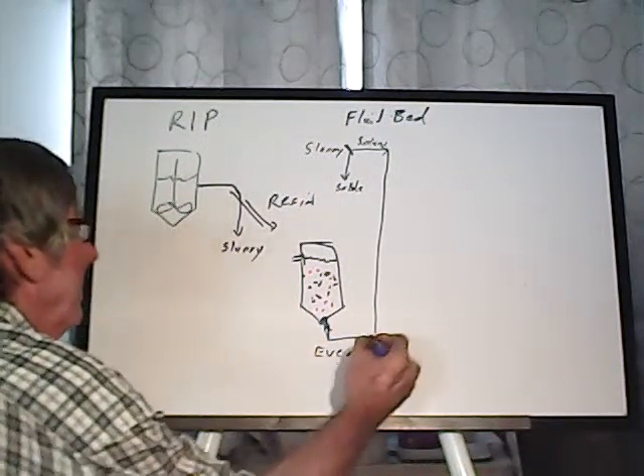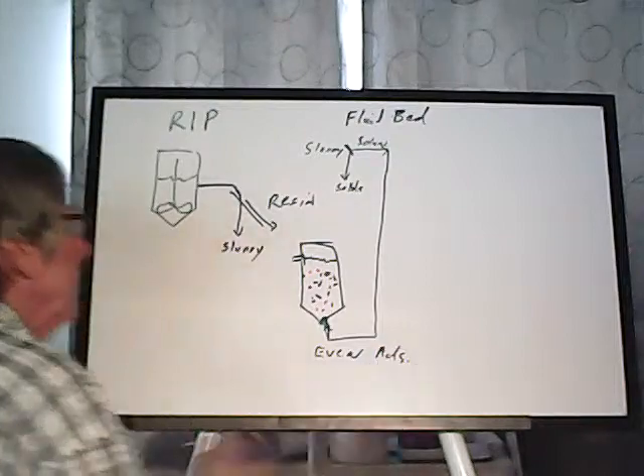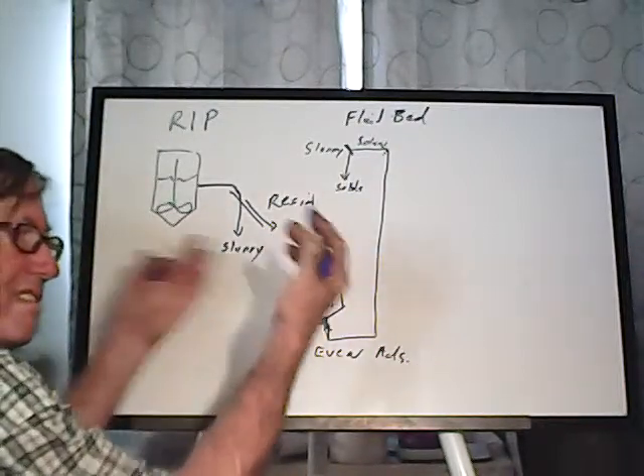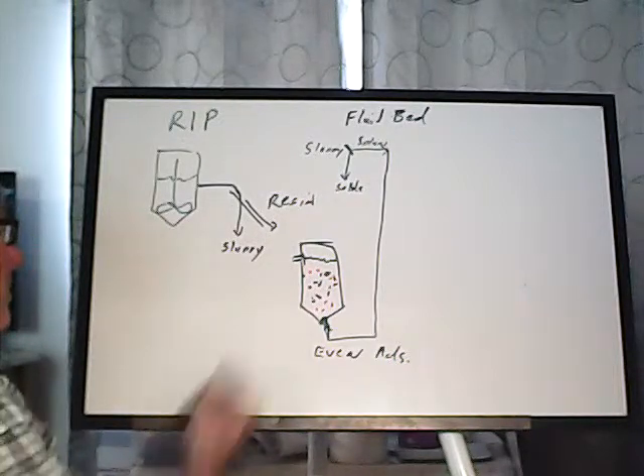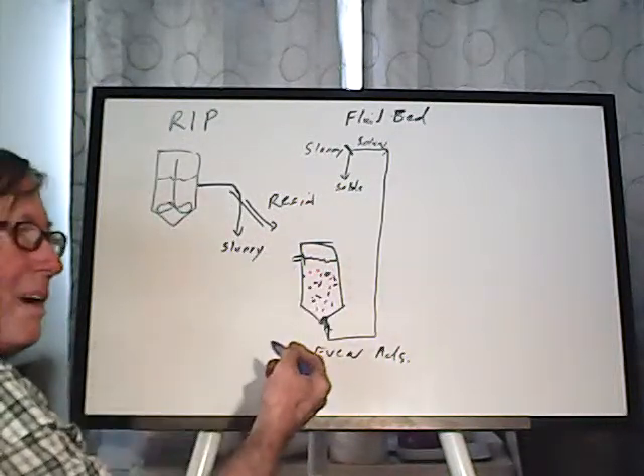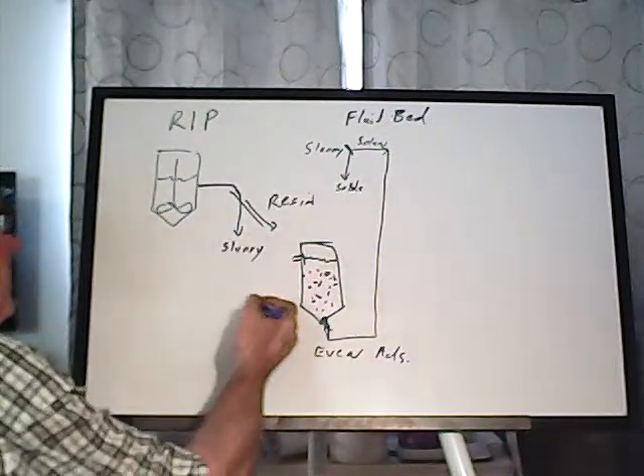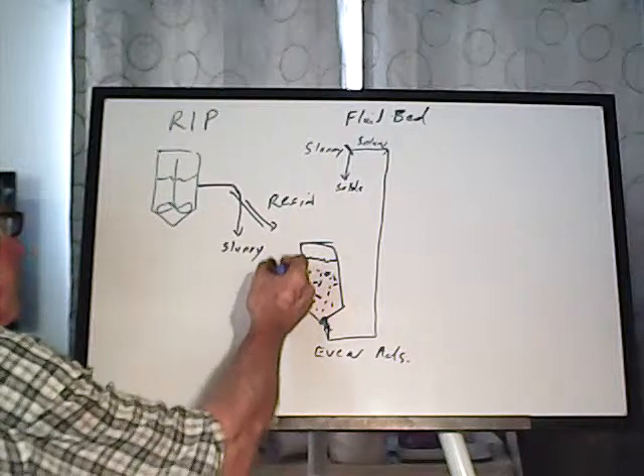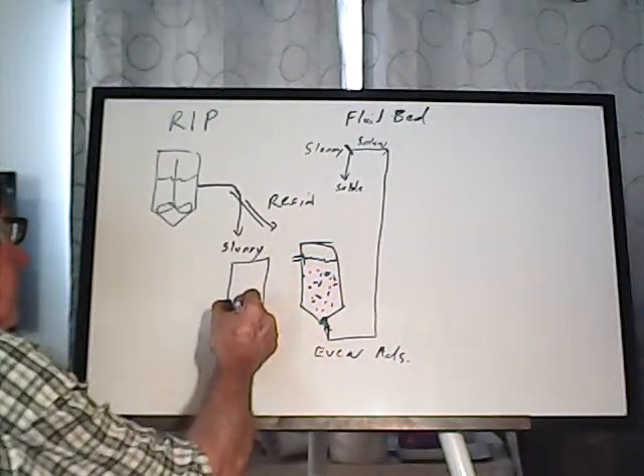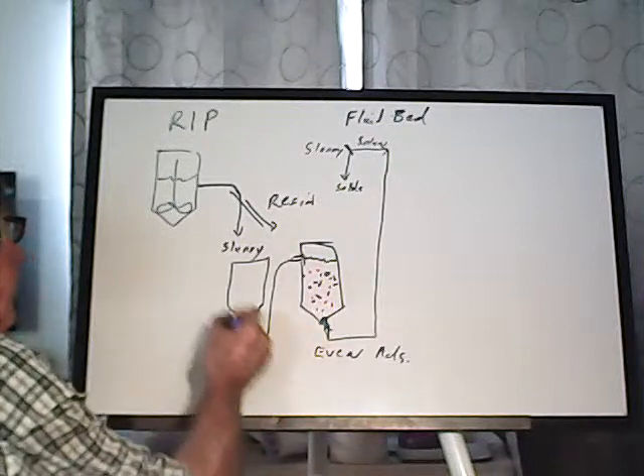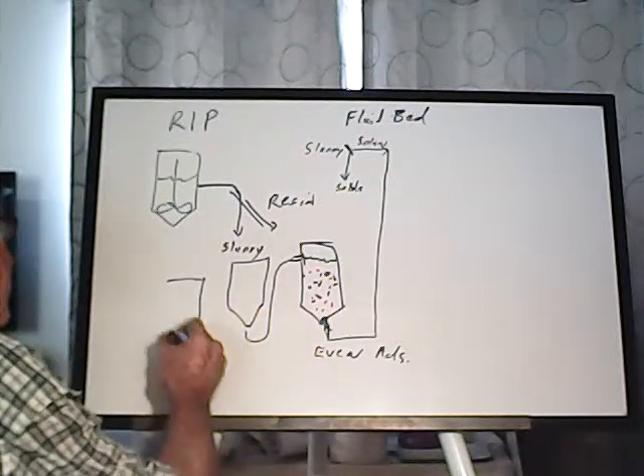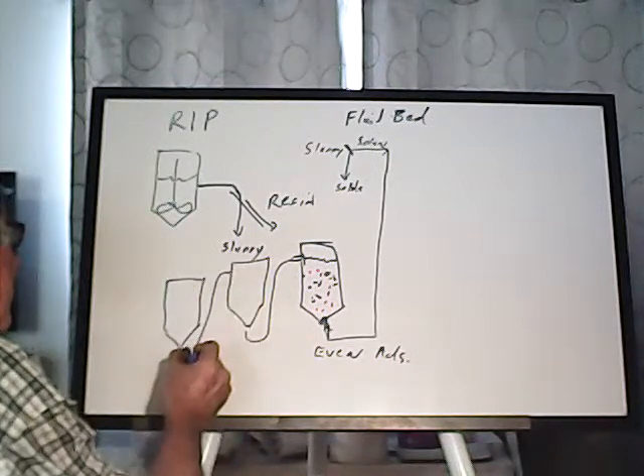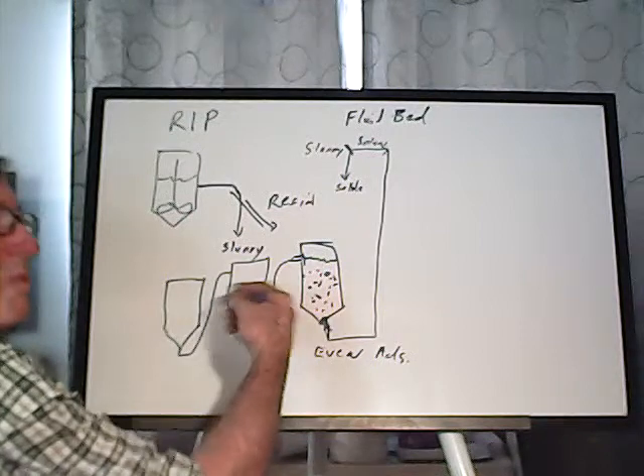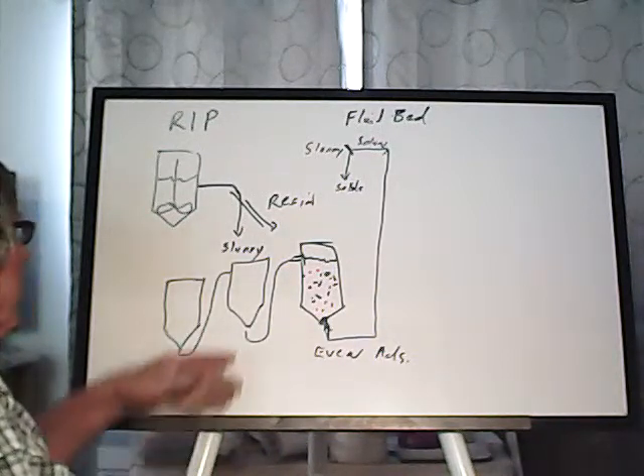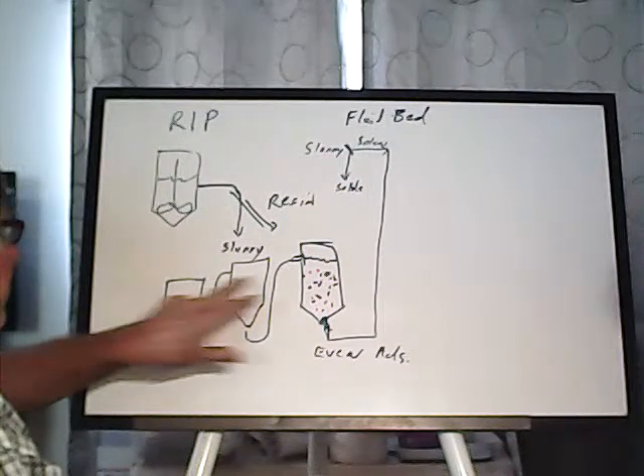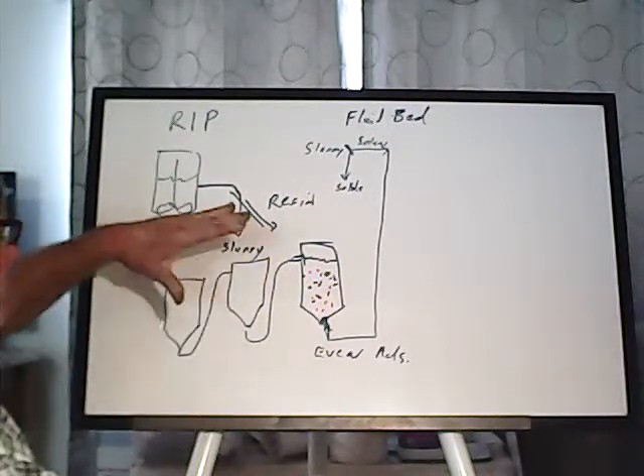Now, the advantage to fluidized bed is that it is very good at even adsorption. Everything gets to the resin fairly easily, so you don't have any dead spots, you know, resin where the stuff's just bypassing it. The problem is, due to equilibrium, you're going to need a series of these, because this is only going to absorb so much before your equilibrium slows down the absorption. So this would be your primary, secondary, tertiary, like that.